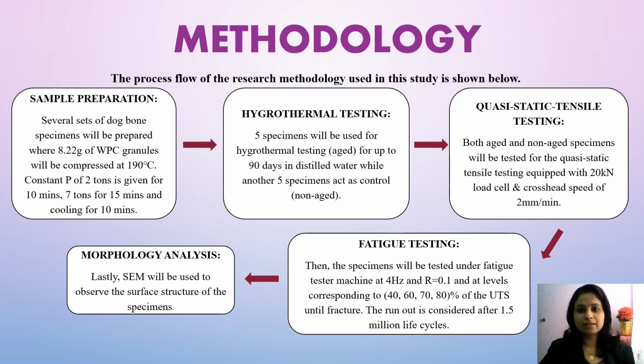After that, fatigue testing. The specimens will be tested under a fatigue tester machine at 4 Hz and R equals 0.1, at levels corresponding to 40, 60, 70 and 80% of the ultimate tensile strength until fracture. The run-out is considered after 1.5 million life cycles. And finally, morphology analysis, where SEM will be used to observe the surface structure of the specimens.